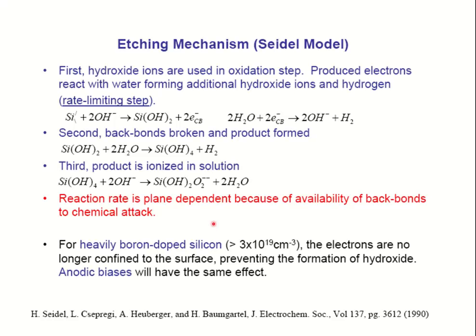For heavily boron doped silicon, electrons are no longer confined to the surface, preventing the formation of hydroxide. So in that particular doped silicon, you should think about that: this doping prevents the formation of hydroxide. So in that case, you should find another way. Anyway, the silicon fabrication process has been researched plentifully, so you can easily find out what to do for a particular silicon etching.